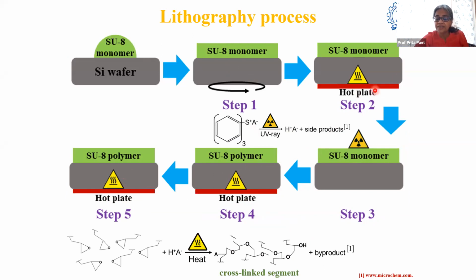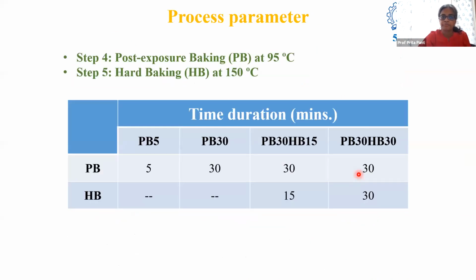This I definitely need to do because I need to get rid of the solvent before I do this UV exposure. So we do this. We do the post-exposure bake at 95 degrees, and we do a hard bake at 150 degrees. These are the two steps 4 and 5 from the previous one. And this is the variation that we have done.